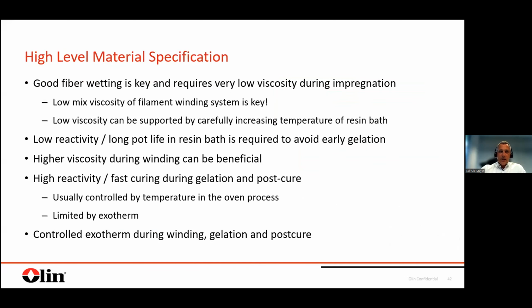All right, if we combine this back into a high-level material specification, my clear statement is that good fiber wetting is a key requirement, and this requires very low viscosity during the impregnation stage, whatever resin you use. This is a key requirement, because if you have flaws in impregnation here, if you have air entrapments at this point, you will carry them on through the process, so you will have an impact on the quality of your pressure vessel. This can be supported by carefully increasing the temperature of the resin bath. And this is where we can help you with reactivity data of our resins to find the right adjustments.